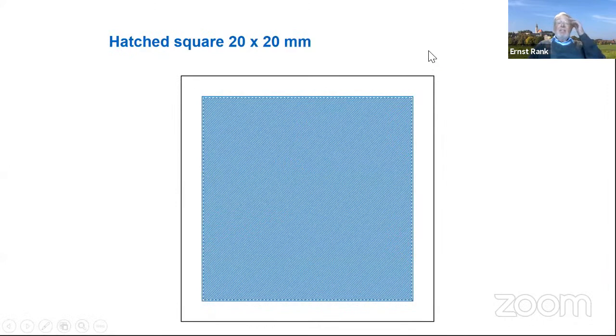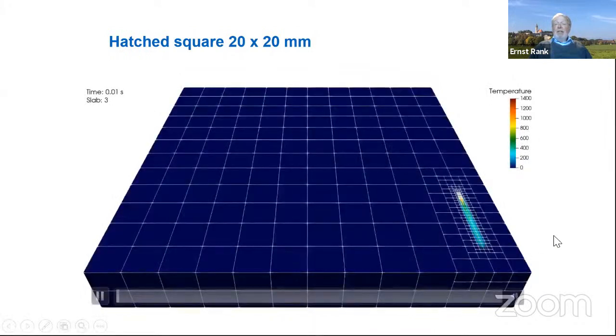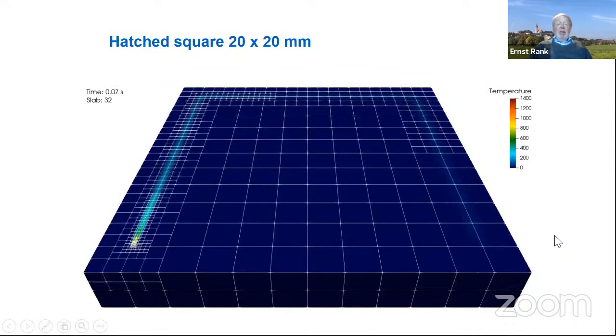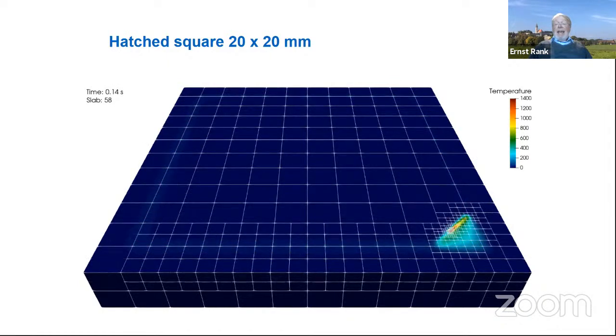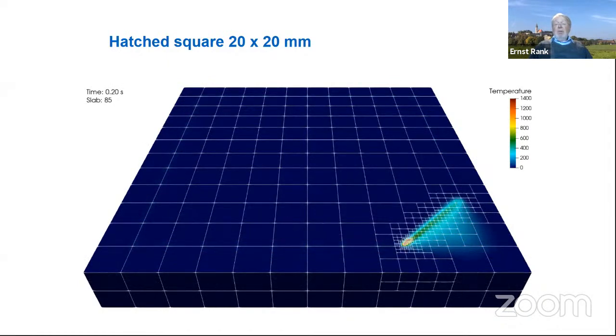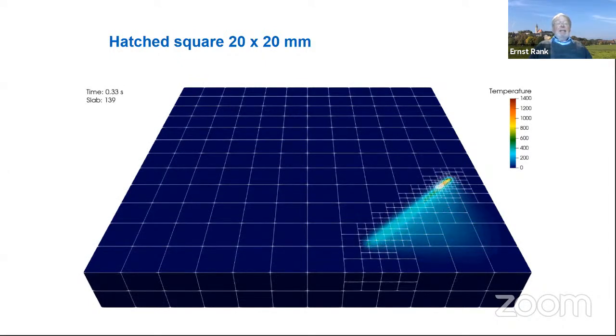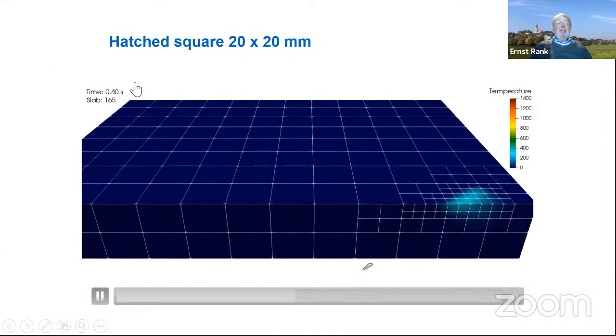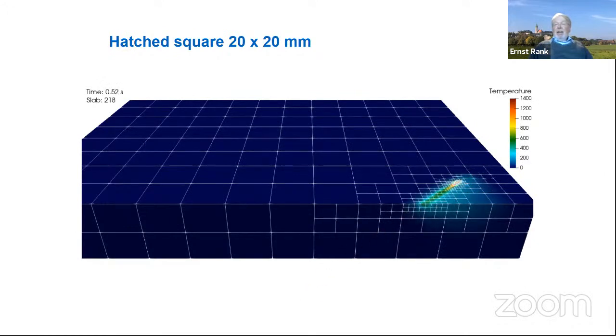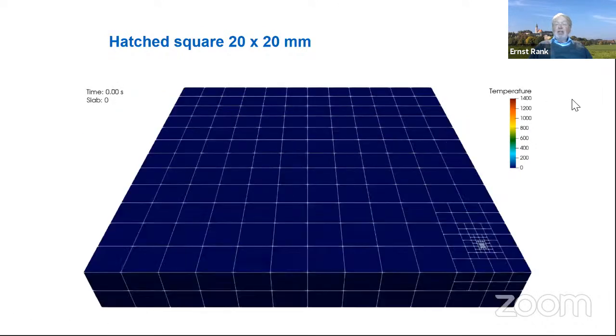Now let's look at this hatched square which we are having. And well, now you see the laser running first around and then hatching in the diagonal. And what is important, you see the spatial adaptation. And on the right side up, you see the slab. So this is the time adaptation which you are having. So that you can see in this cut, it's really 3-dimensional. So you get a refinement and de-refinement also in the depth direction of this structure.